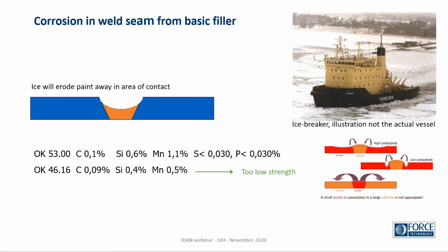If we should minimize the amount of silicon and manganese to avoid these sensitive microstructures, we could look into, what should I call it, a very ordinary rutile electrode like this one, just as a thought. But in the end, it would have too low strength and probably also too little impact toughness for this application. What was done, as I recall, was to increase the alloying with a little nickel to get an overall higher corrosion resistance of the weld metal.